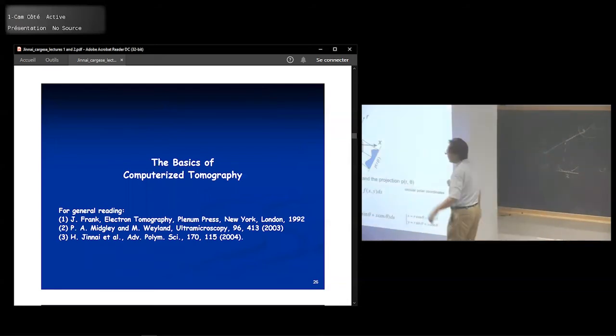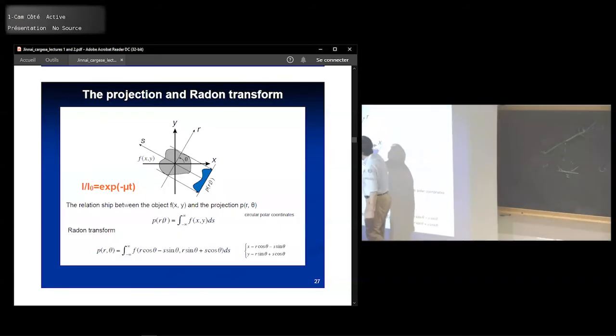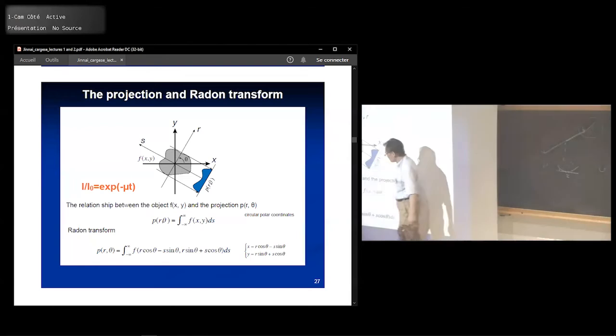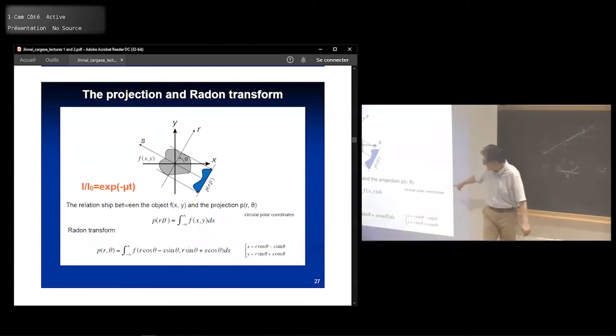So some mathematics. No, it's not very mathematical, but you have a sample, and in this case, this is a two-dimensional sample, and you shine the X-ray or shine the electrons through this sample, and then you take projections. Projection is P. The background is that the intensity changes with the thickness of the sample in this way. That's the thing you have to fulfill. And then the projection can be written like this. Okay, so it's a simple way. And the coordinates are x and y, and then theta and r. That's circular polar coordinates. You can change the coordinates into circular polar coordinates too.